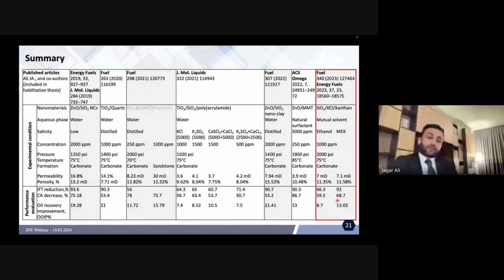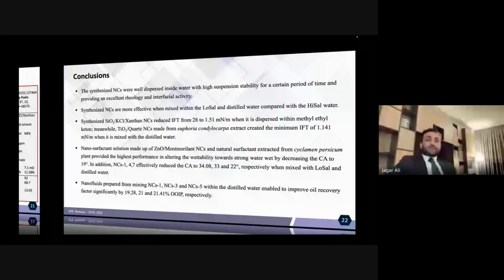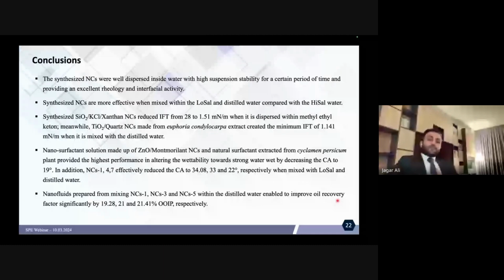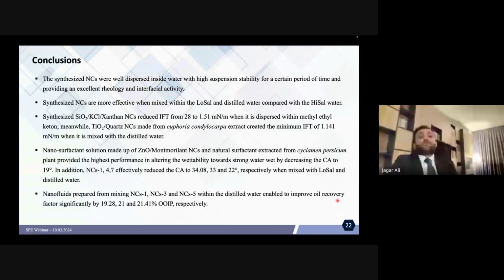So it can be summarized that the nanocomposites that we use to prepare nanofluids are more effective with distilled water and with low salinity water in terms of reducing the IFT, changing the wettability, and improving the recovery. But we noticed from our studies, when the IFT is highly changed, we have better oil recovery compared with the wettability alteration.